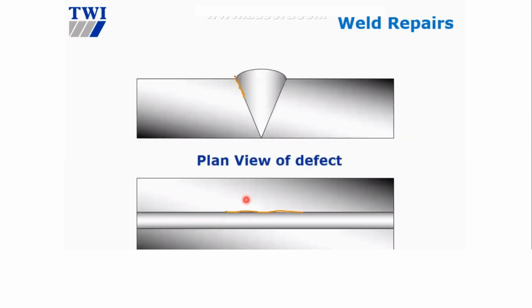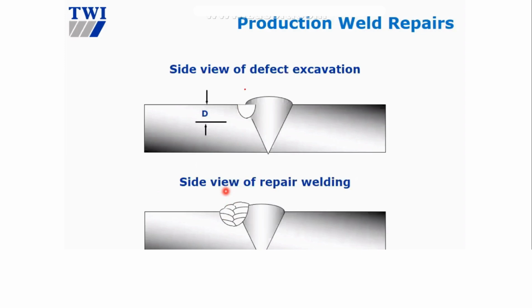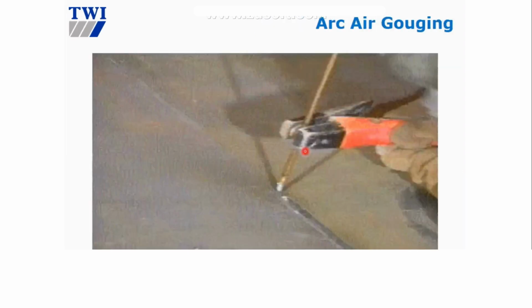Example, this is what we have from the cross-section view, and this is from the top view, the length of the defect. Normally, we need to excavate or grind more than the depth, more than the length. Like this, right? Previously maybe the crack is up to there, then we need to dig more, excavate more, to make sure that there are no traces of crack still there. And we can use arc gouging.